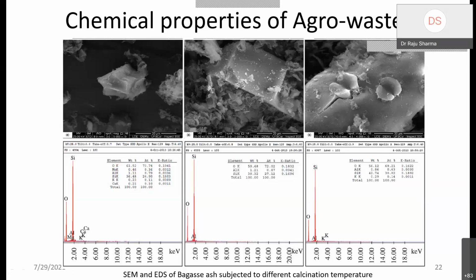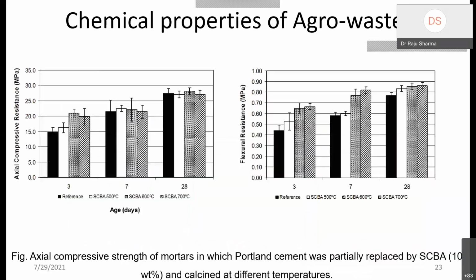I'm saying it's an individual material, right? So it increases the chemical composition, which may give you an advantage when using it in concrete. And yes, it is advantageous here when they replace cement with this sugarcane bagasse at a fixed 10 weight percent. So SCBA is replaced with cement at 10%. The variable is the different temperature, the final product of the different temperature.